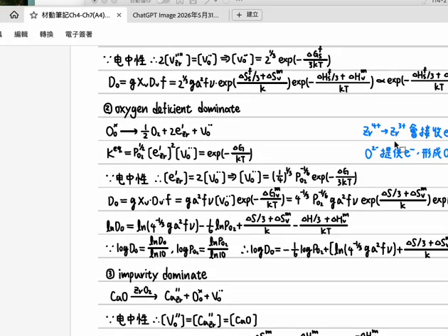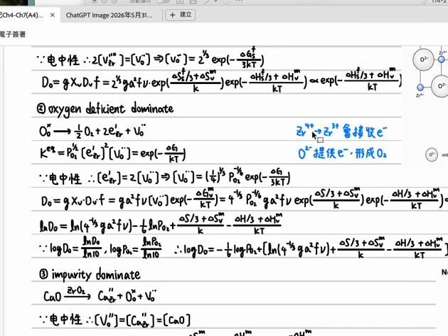Which means that the 4 positive charge becomes 3 positive charge, which means that it receives the electron. And which may also imply that somebody gave Zr the electron. So who can give Zr the electrons will be oxygen with 2 negative charge. So that's why we will write this down. So oxygen ion at oxygen site is neutral, but actually it has a 2 negative charge.